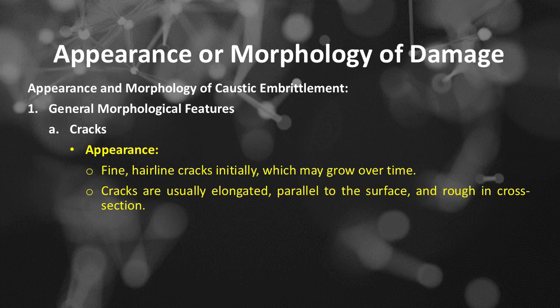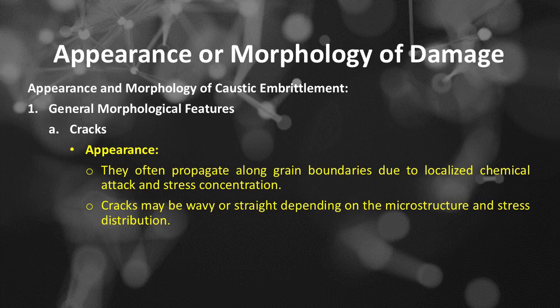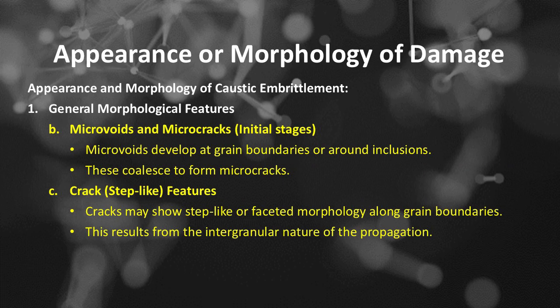Cracks are usually elongated, parallel to the surface, and rough in cross-section. They often propagate along grain boundaries due to localized chemical attack and stress concentration. Cracks may be wavy or straight depending on the microstructure and stress distribution. Feature number B, microvoids and microcracks. Initial stages: microvoids develop at grain boundaries or around inclusions. These coalesce to form microcracks.